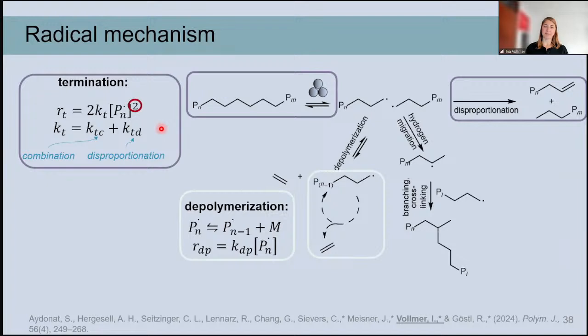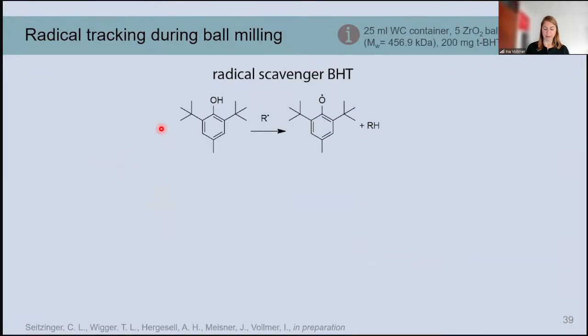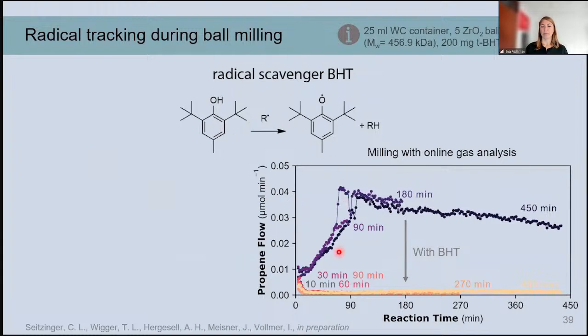To study this mechanism a bit more, we had to measure this radical concentration in the reactor a bit better, and especially the initiation rate of the radicals. Again, we use this trick of putting BHT into the ball milling chamber, where this OH group gives off the hydrogen to terminate the radical. And what we can then observe is the loss of this OH group. Here you can see again, when milling with different times, we form propene. And if we do that with the BHT, we never see any propene because it is suppressed.